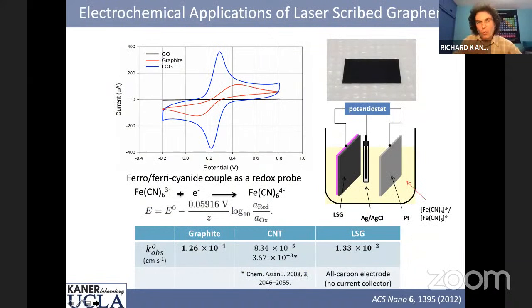All right, now, one of the things we looked at is we were interested in the electrochemistry of this material. And what's interesting is if you look at the peak separation, and this is a current potential curve, so this is a cyclic voltammogram, the peak separation approaches the theoretical limit. It's 0.0595 volts. And here's the Nernst equation down here, and the theoretical limit is 0.05916. So this is a real experiment. It's not quite at the limit, but it's about as close as you can get.